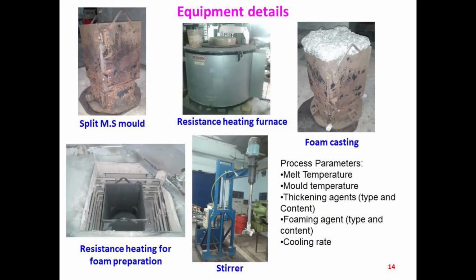And these crucibles should be split type crucibles, because after foaming you should take out the foam. So every time you have to use the split type of crucible. This crucible is put within the furnace, and then we add all these things and do the foaming, and this is the crucible with foam. After that, the crucible is split into two parts, and we take out the foam billet.